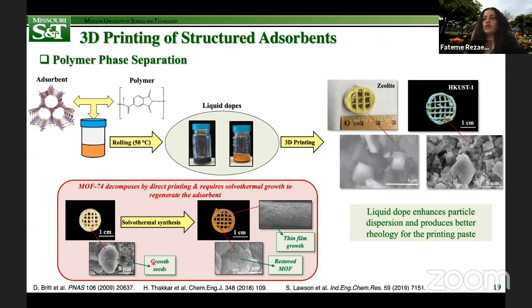So we use them as seed, basically seed growth particles, to generate a film on the surface in a secondary solvothermal synthesis step, as you can see here. And this small SEM image clearly shows the formation of crystalline phases of MOF-74. Overall, this is a promising method, and the formation of a liquid dope enhances particle dispersion and produces better rheology for the printing paste. However, as I mentioned earlier, the loading obtained by this method is limited,